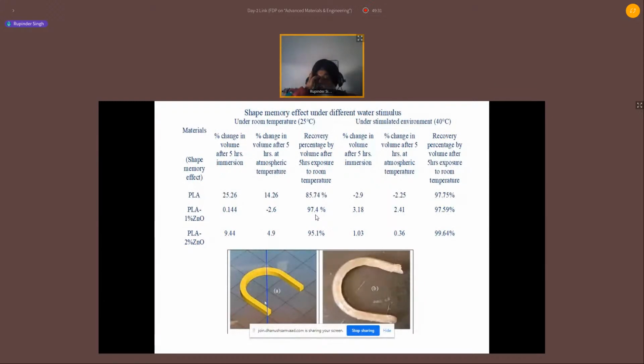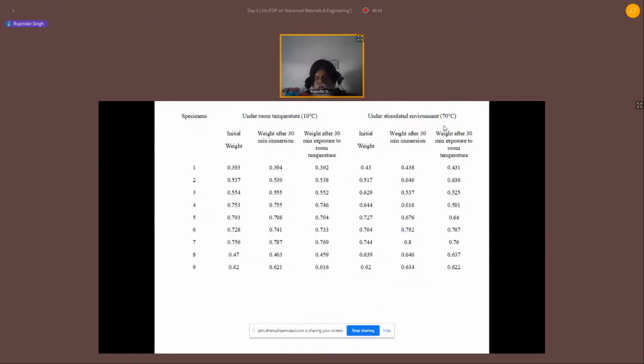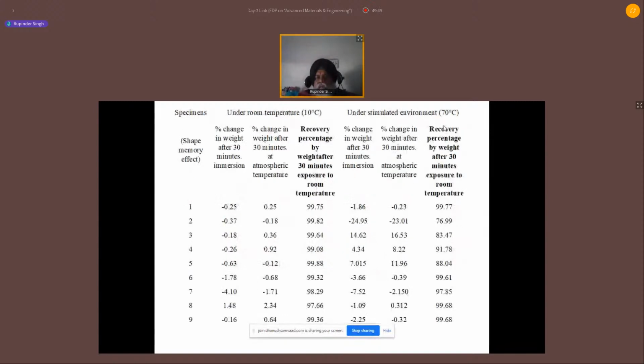So what we observed is there was an effect of the temperature. At different temperatures, this behaves in a different manner, like at 40 degrees. Then we tried to see this material's behavior at a very low temperature, and then at the glass transition temperature. And we observed that 99.9% recovery is also possible. So this can be really helpful for me as a 4D material for some typical sensor applications, right?